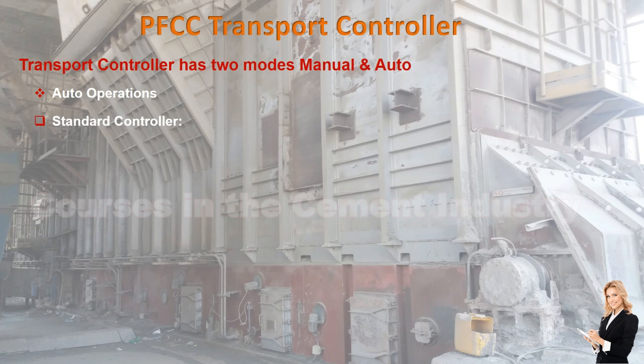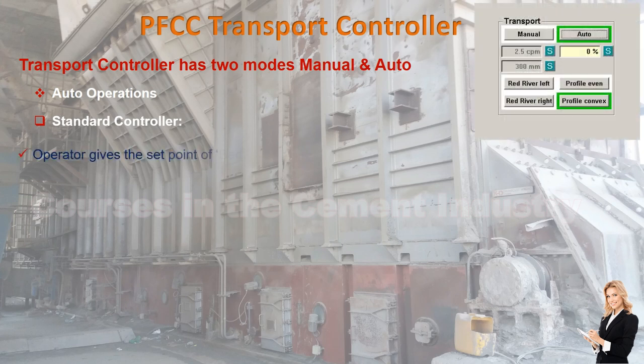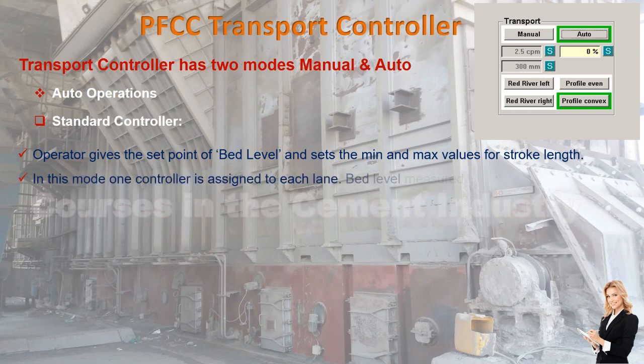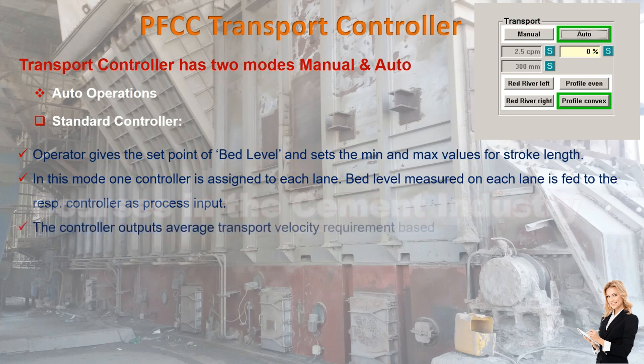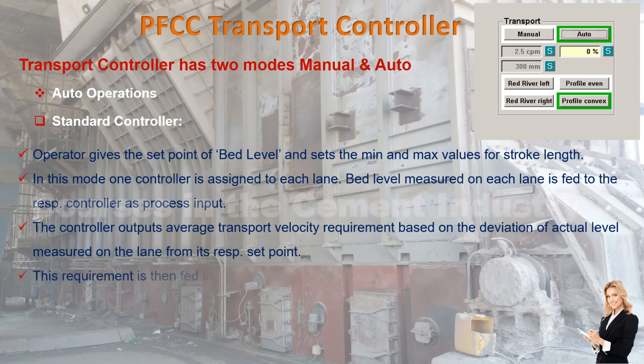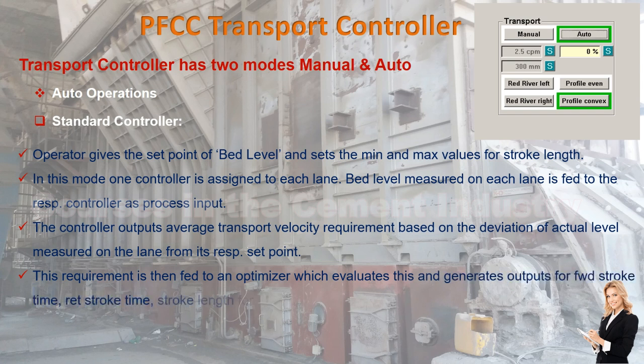Standard controller. 1. Operator gives the set point of bed level, and sets the minimum and maximum values for stroke length. 2. In this mode, one controller is assigned to each lane. Bed level measured on each lane is fed to the respective controller as process input. 3. The controller outputs average transport velocity requirement based on the deviation of actual level measured on the lane from its set point. 4. This requirement is then fed to an optimizer, which evaluates this and generates outputs for forward stroke time, RET stroke time, stroke length for each lane, and CPM output common for all lanes.